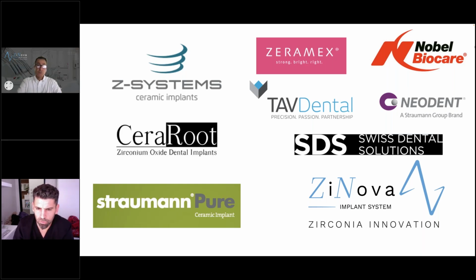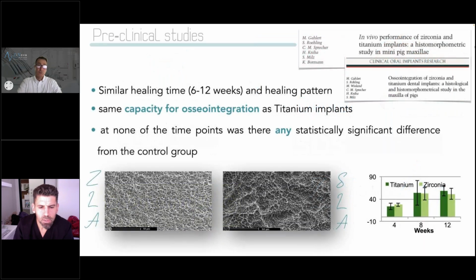an alternative to titanium. So what's so good about zirconia? What data do we have? What does the science show us about zirconia? Well, in this preclinical study in mini pigs, they simply compared the osseointegration time between zirconia and titanium implants with a similar roughness and surface pattern, as you can see in the two images. And they saw that there was similar healing time at 6 to 12 weeks and healing pattern.